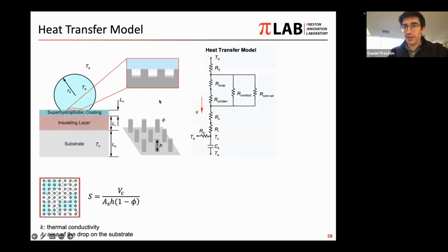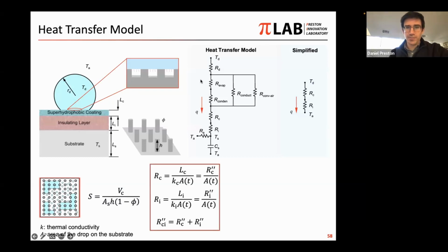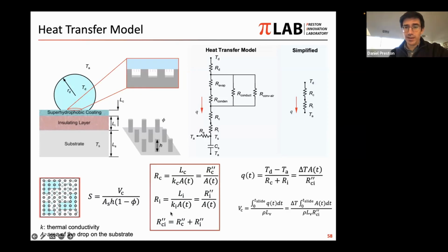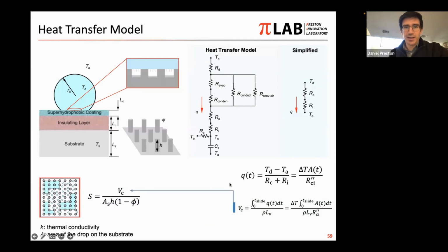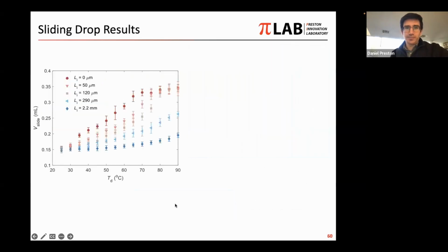We did some heat transfer modeling to try to model the process. There's a full network here, but we found that we could make some assumptions and simplify it to the one that's shown on the right-hand side of the slide. And from here, we can combine the two thermal resistances for the superhydrophobic coating and the insulating layer, and basically use this to get the heat transfer. Heat transfer is a function of time in this case, and it also has to be integrated over time to get the total volume of the drop right before it detaches. So we basically apply some analysis here, do all that to get this volume, and this is going to be the volume that we get at the departure.